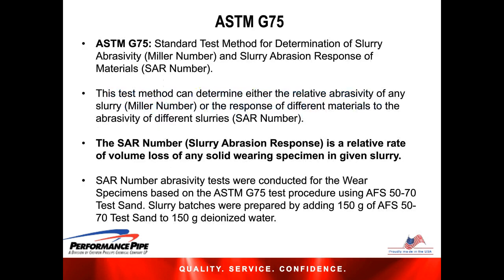Just a little bit about the details of the ASTM test by which these tests were conducted, ASTM G75. That standard is a standard test method for determination of slurry abrasivity, which then allows one to determine a Miller number or the slurry abrasion response of materials, in which case the results are represented as an SAR number. This test method can determine either the relative abrasivity of any slurry or the response of different materials to the abrasivity of different slurries. And so there's some flexibility in terms of how the test is conducted.